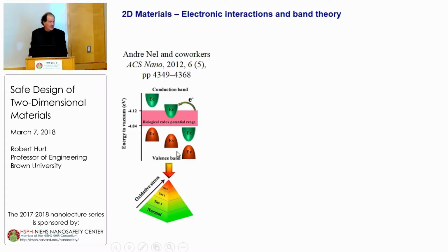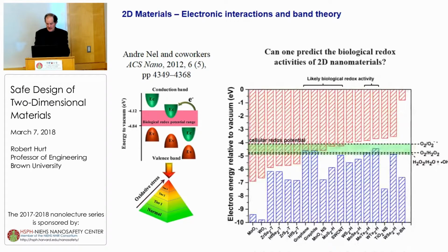And this is for semiconductors. If you take the valence band for semiconductors and the conduction band, and look at the location of those allowed energy levels relative to this biological redox potential range, you can identify some materials that will either accept or give up electrons at the same energy level, and thus they can participate in permissive electron transfers and interrupt the natural cellular redox processes. And this particular case shows a material with a conduction band, which would normally be empty, but has allowed electron energy levels in the same range, and could therefore interrupt and be redox active in a biological system. And you can plot these for 2D materials.